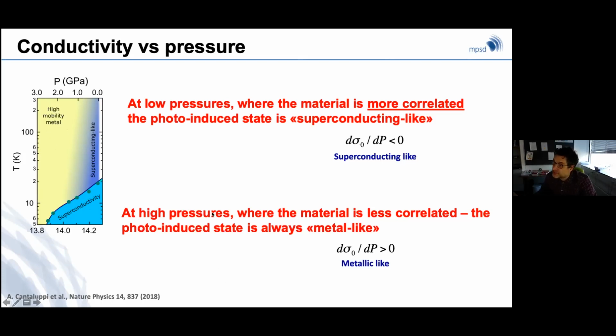We find something that perhaps is not really so superconducting, but looks more like a high mobility metal, as defined by a figure of merit that I've arbitrarily decided is enough for now, that is d sigma 0 over d p bigger than 0, okay? But this is taking us to a place where we can now make statements where we say that the material should be strongly correlated and possibly fluctuating, and I will get to that in a second, if I want the system to be superconducting.